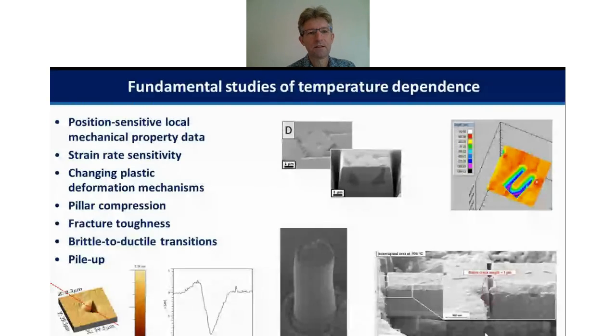So as well as these temperature tests where you really need to know the high temperature hardness, there's a wealth of other information you can get out of these nanomechanical tests when you have reliable data. You can get, for example, position sensitive local mechanical property data in different phases. In the example in the middle of the slide here, you can see a cemented carbide, cobalt with tungsten carbide grains in the cobalt matrix, and you can see a little indent in a carbide grain. I'll show later how you can use these tests to get very sensitive information about the mechanical properties at high temperature of the individual phases.